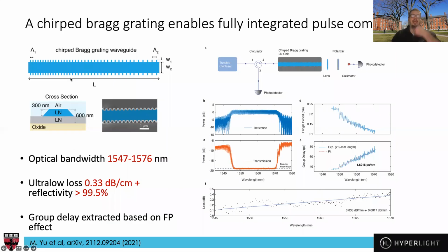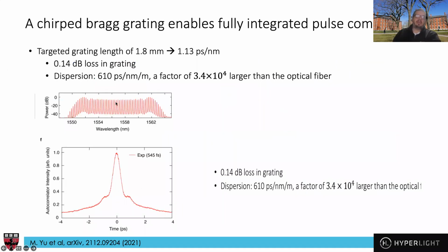The device works in reflection, so we get 99.5% reflectivity of light. So basically, a broad optical pulse comes in for several picoseconds and gets pushed back and compressed, and we get about a 500 femtosecond pulse. So this is experimental data, which shows the pulse that emerges from this device and the comb spectrum.